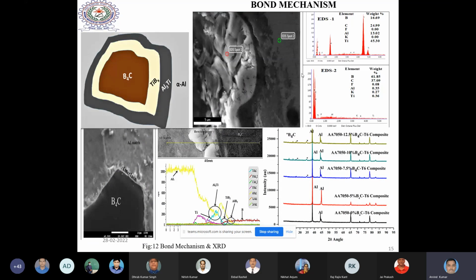The motive was to develop a reaction layer. Actually, when the B4C particle comes in contact with the aluminum matrix with the assistance of flux, there is a local increase in temperature. The melting temperature of B4C is around 2300 degrees centigrade, and aluminum is 660, so there is a huge difference between the two melting points. If it is not melted, then we'll have a solid liquid mixture. So we have tried to put some reagent which locally increased the vicinity temperature of the B4C particle at the periphery. There it reacts with the aluminum matrix and forms a layer. Layer means, here you have shown one block.